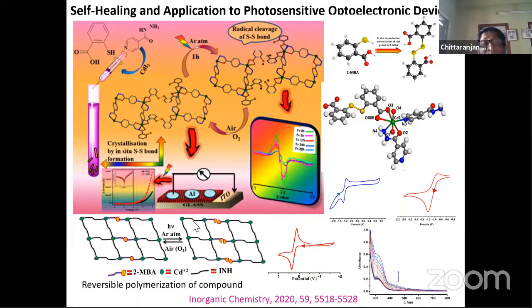Herein, upon light radiation, this sulfur-sulfur bond clips. Herein you see the cartoon picture shows this sulfur-sulfur bond clips, and thus the molecule dissociates. If you aerate it, or if you pass air oxygen, then it is again reoxidized. It can also be reduced by sodium borohydride type reagent, or can be reduced electrochemically. That also leads to the cleavage of this bond.